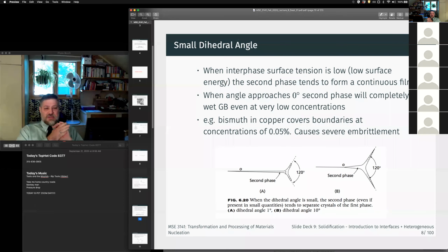And so there are all these mathematical relationships, and to validate those relationships, people wanted to understand, what does the 3D structure of grains look like? So they put bismuth in copper, let it diffuse into the grain boundaries, and then it just fell apart and you had individual grains.